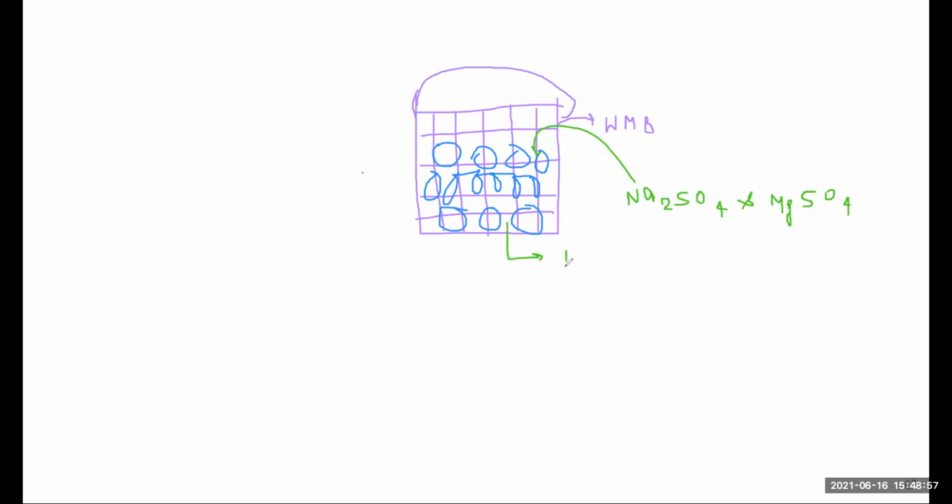Now, this chemical is kept for a period of 16 to 18 hours in this bucket. So we mix the chemical with the aggregate in this bucket for a period of 16 to 18 hours, with the aggregate dipped in the chemical. After that, after 16 to 18 hours, we remove all the aggregates from the sample.